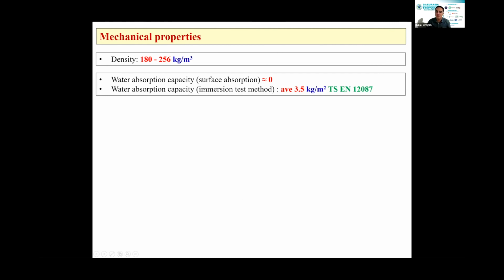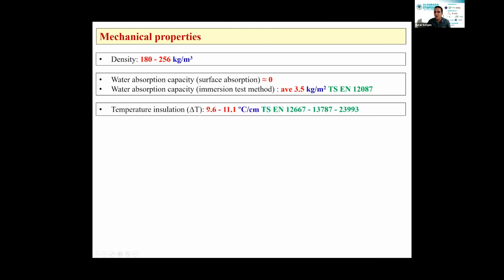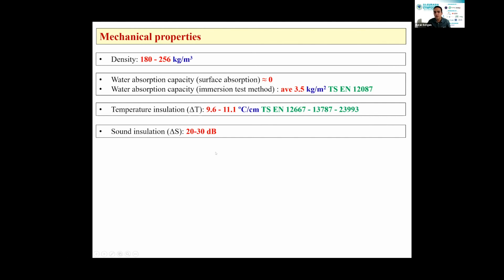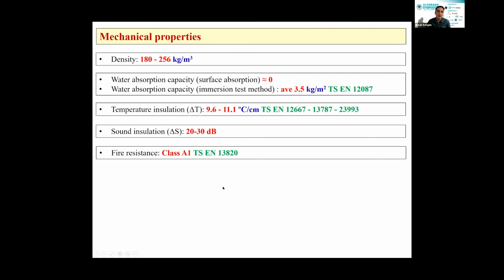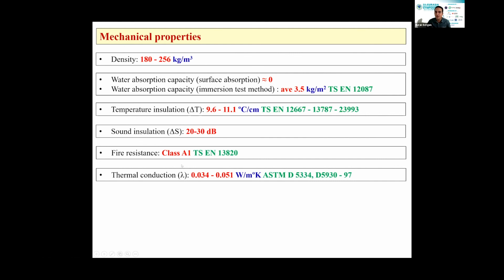And the water absorption capacity, according to the immersion test, can be reached up to 3.5 kilogram per square meter according to these TS standards. But the important one is the surface absorption capacity. The temperature insulation delta T changes between 9.6 to 11.1 Celsius per centimeter. And for sound insulation, we can reach a 20 to 30 decibel sound insulation level. And all of these 6 different specimens have A1 class fire resistance certificate. And the thermal conduction coefficient, lambda, changes between 0.03 to 0.05. The maximum range of this value is given around 0.06 inside this standard,